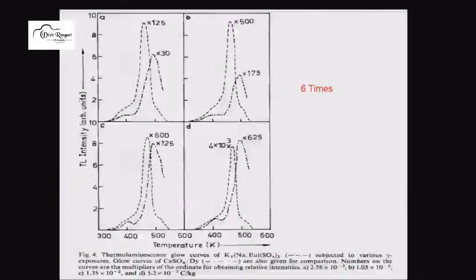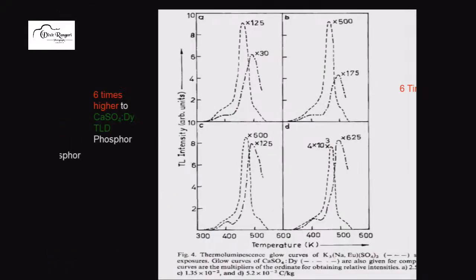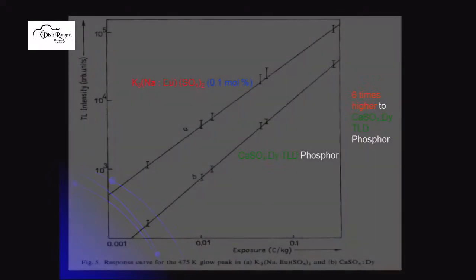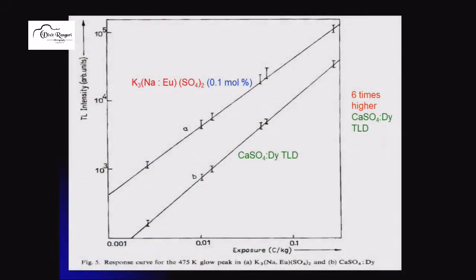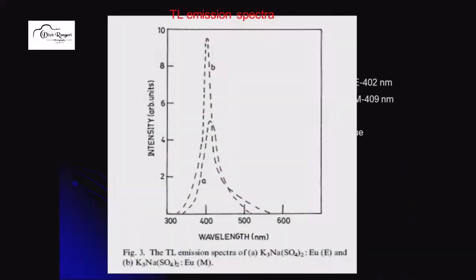So this is the response curve of this. The glow curve does not change, but you can see here the response curve. This is the BARC material, the standard one, and this is our lab material. This is 6 times higher. Then you can measure a very small dose by this material. So this material is very interesting, and the TL emission is also blue color.